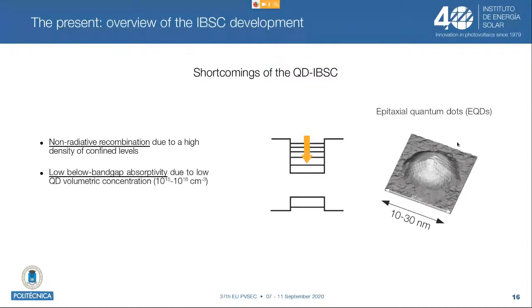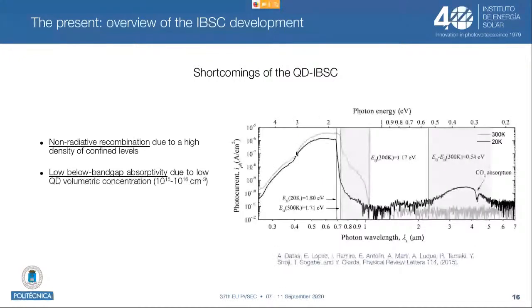Another issue that we have is the low absorption below the band gap, so low absorption in the quantum dots. This is due to the low volumetric concentration of quantum dots, which is on the order of 10 to the 15, 10 to the 16 centimeter minus 3. As you can see here, I have shaded the 2 regions where the quantum dot absorbs. You can see in this graph of photocurrent versus wavelength that the photocurrent produced in the 2 shaded regions is much weaker than the one above the band gap. So still, the absorption needs to be enhanced a lot.